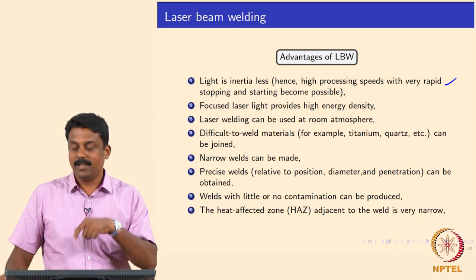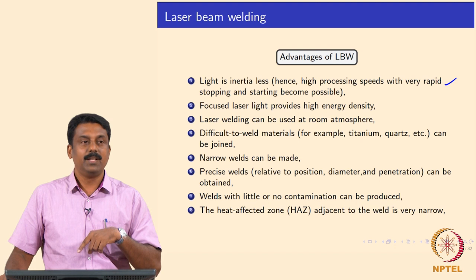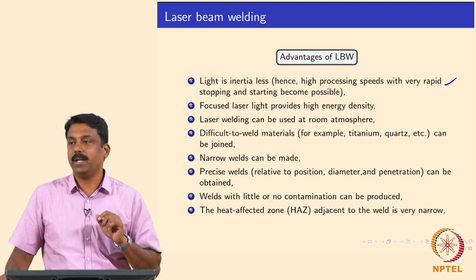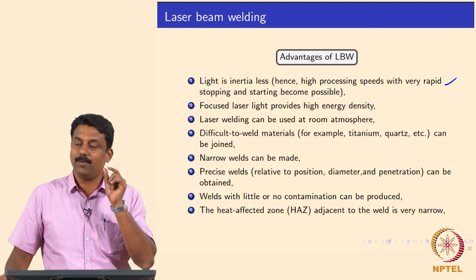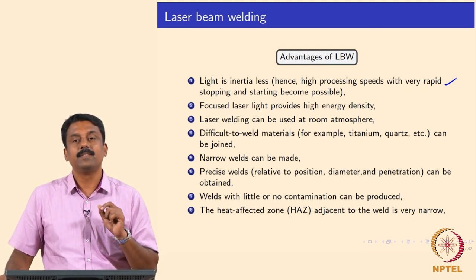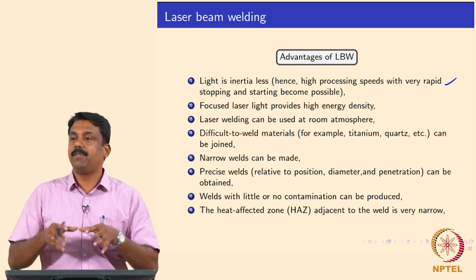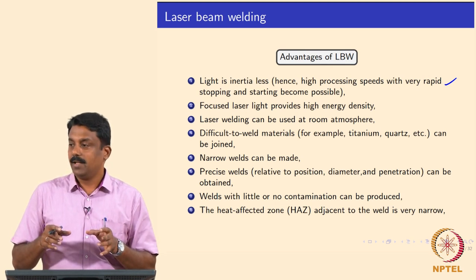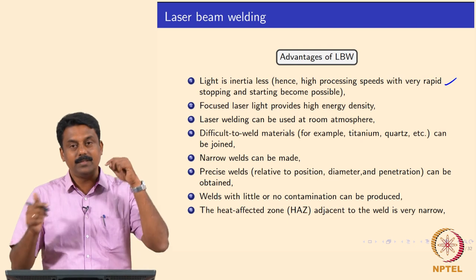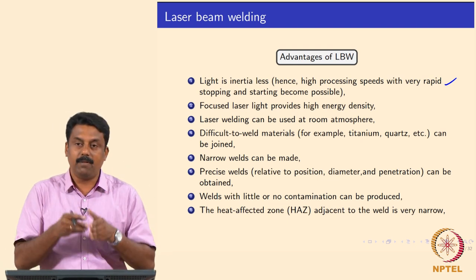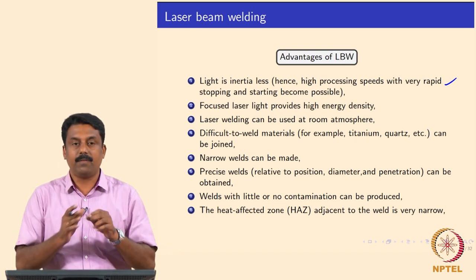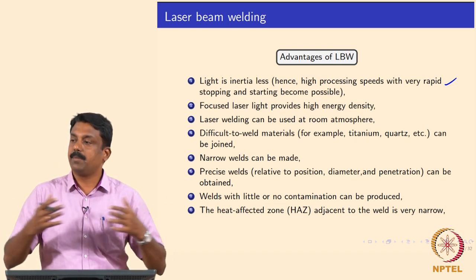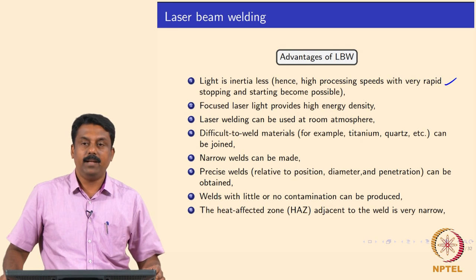We can also focus the laser into a very tiny spot. The laser I showed you in the videos had a spot size of 50 microns. 4 kilowatt power can be focused onto a 50 micron spot size - an enormous amount of power density. With that we can concentrate the laser power into a very tiny area, so we can increase the depth of penetration without affecting the microstructure of the material widely.